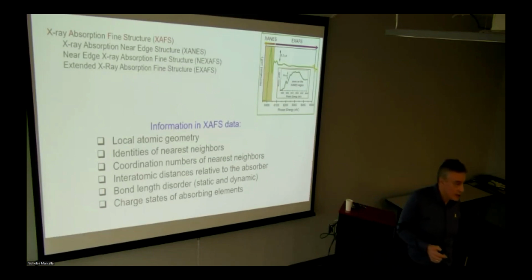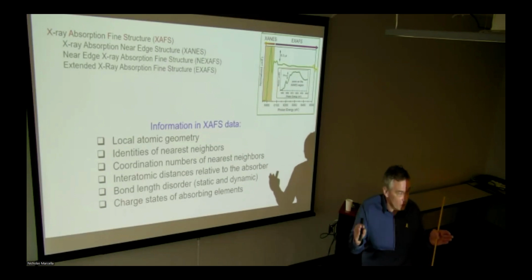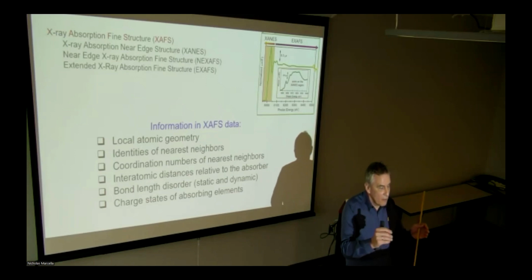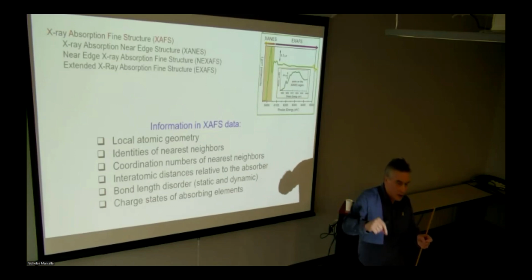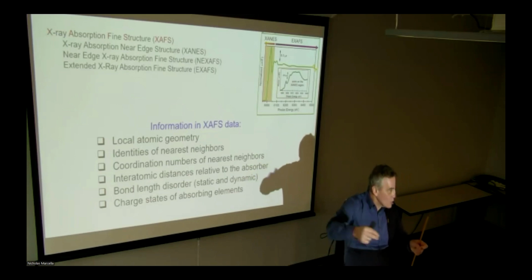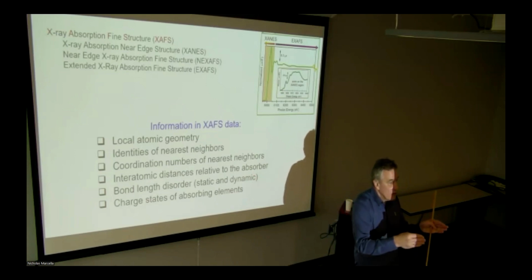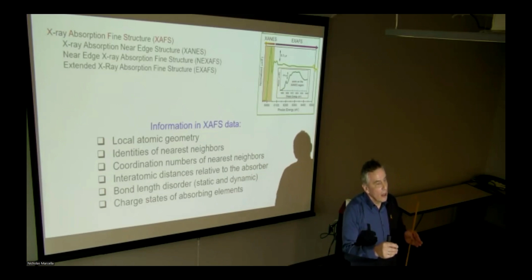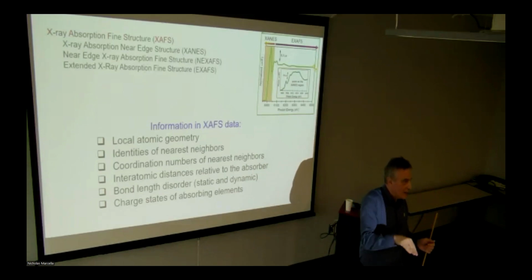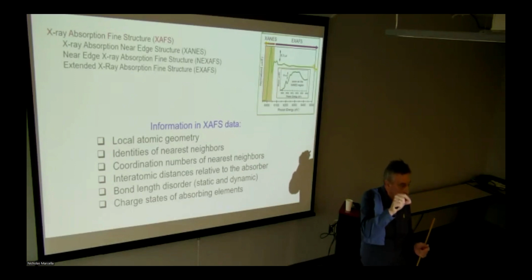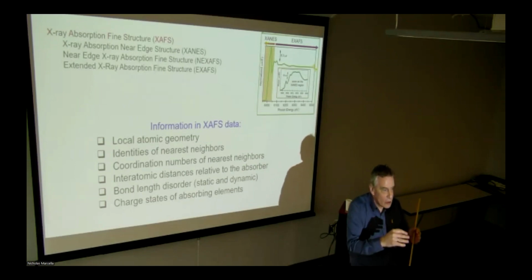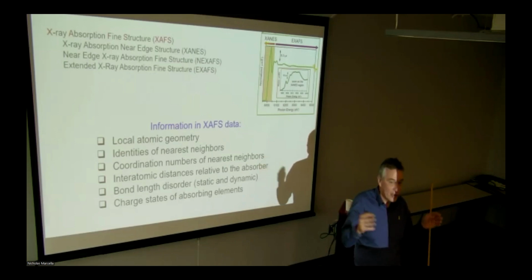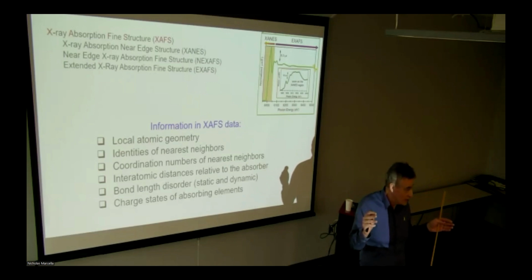What does it mean, short characteristic time? The photoelectron, when it comes out of the atom, does not continue in this excited state for a long enough time that the atoms probed by this electron will have enough time to vibrate, to move around, so that all their distances will be averaged out. It's not going to happen, for the simple reason that the core hole that is left in the core state when the electron is excited will easily be filled by higher electrons performing a reverse transition. As soon as this happens, the outgoing wave stops emanating, and the interference will be gone. You need two waves for it, outgoing and scattered.